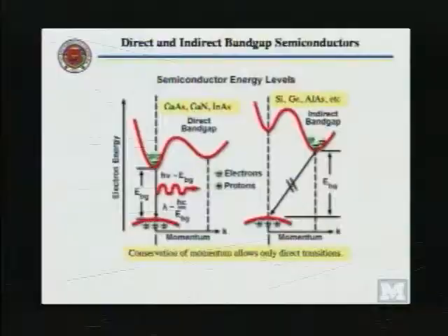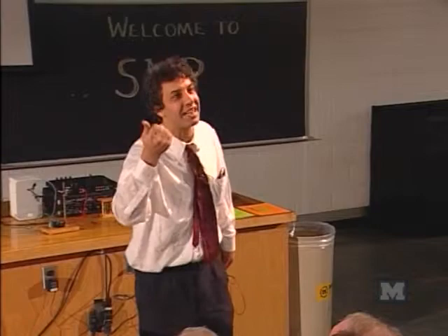When we do the quantum mechanical description of the thing, I sort of said energies and band, but if you want to look at it in more detail, one should look at not just energy, but also momentum, or crystal momentum. And it turns out when you put electrons in, they end up right at the most energetically favorable place, right here. And the bubbles, the holes, end up right here. In certain semiconductors, these things are aligned. And when they are aligned, they can recombine, and for each electron, you would get one photon. You would get light out of it.